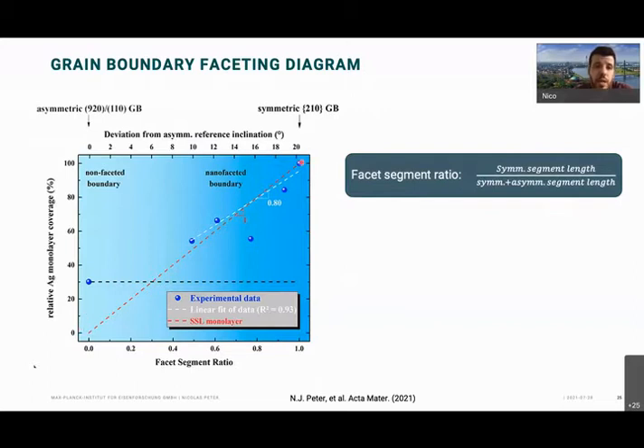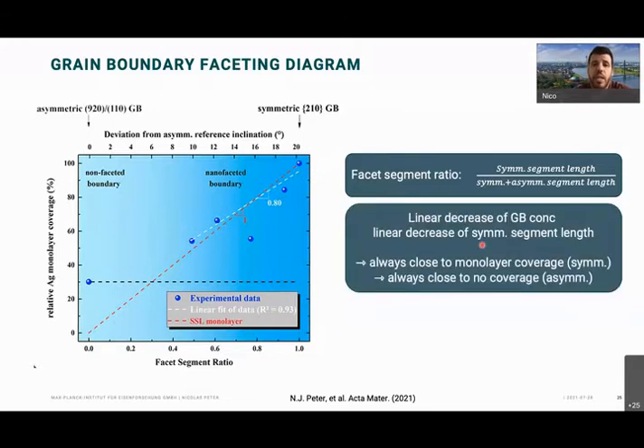And what we do is we take a red line from the very surface where we assume monolayer coverage, which is 100%. And then at 0, we should be at 0. So if our facet segment ratio is 0, we have no symmetric silver containing portions. We should have no monolayer at all anymore. So this is this red line here. And then we measured, of course, different points at different facet segment ratios and fitted them and found that the agreement is fairly good. So that means that actually the silver concentration linearly decreases with the symmetric segment length. That means also that our assumption means that the monolayer is pretty much always at the symmetric facet segment, while the asymmetric segment is almost always completely silver free.